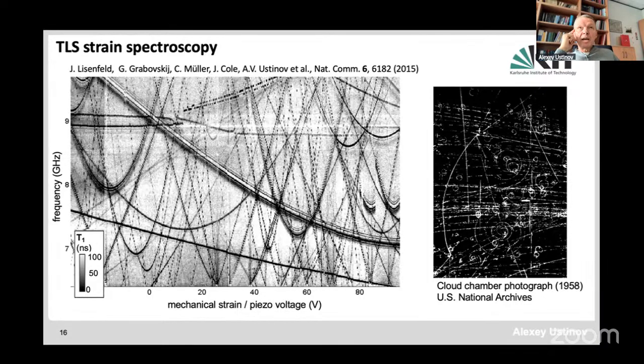So we can have strongly coupled defects. In this case, during the time at the defect, the excitation can perform several swap exchange oscillations between the superconducting qubit, the artificial two-level system, and the natural, microscopic defect in the circuit. So for strongly coupled defects, we observe those shades. But you also see, really interestingly, that some of these lines are interrupted in a random way. This is like telegraph switching due to the presence of incoherent defects next to the coherent one. Some of these defects also show interaction with each other, which I'm not going to discuss today. So really a variety of very interesting properties.